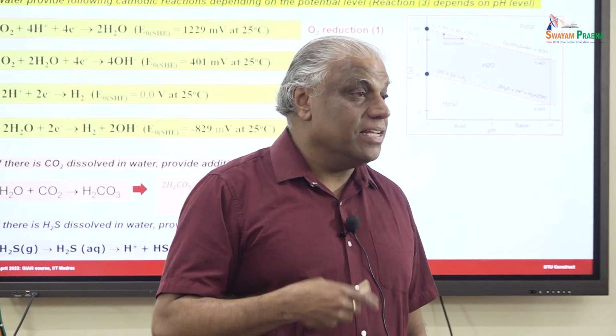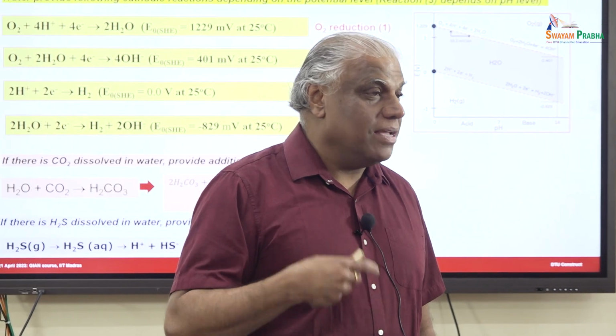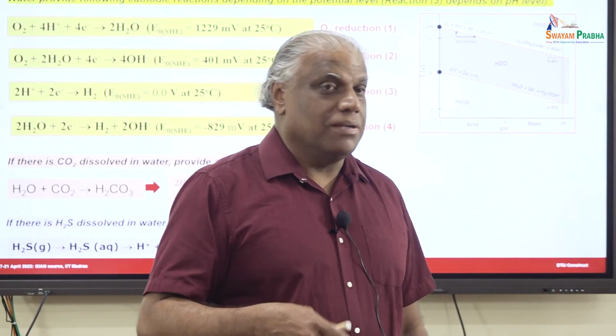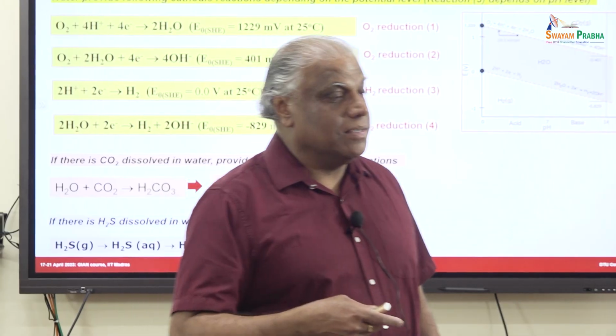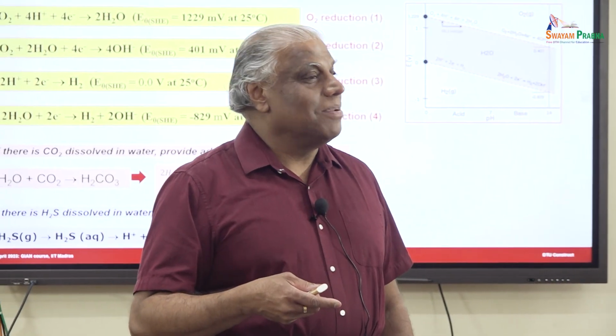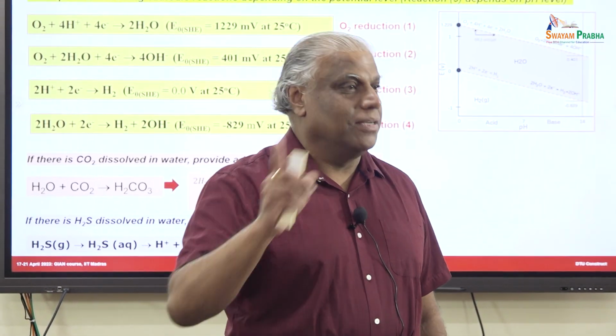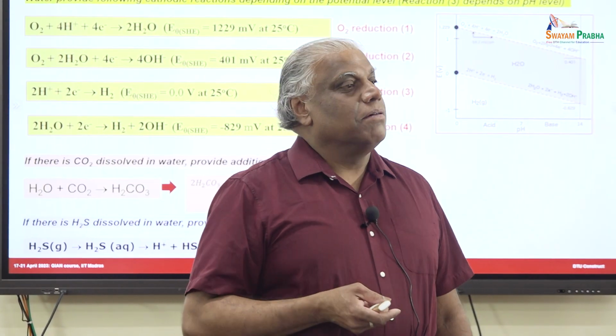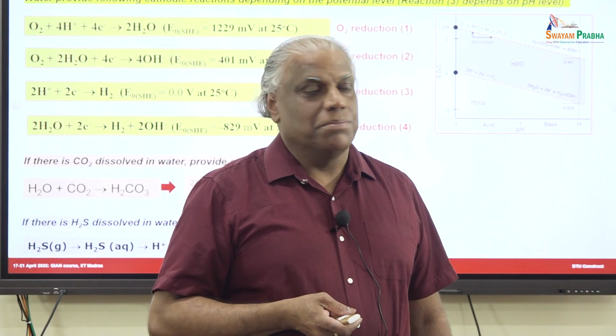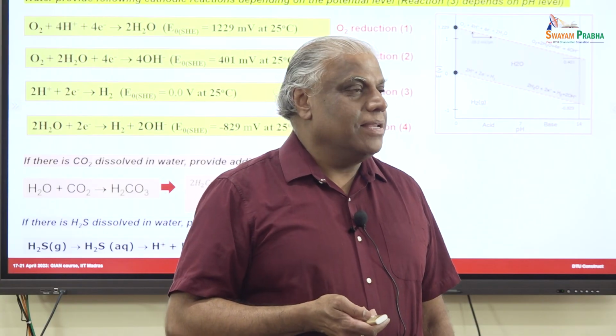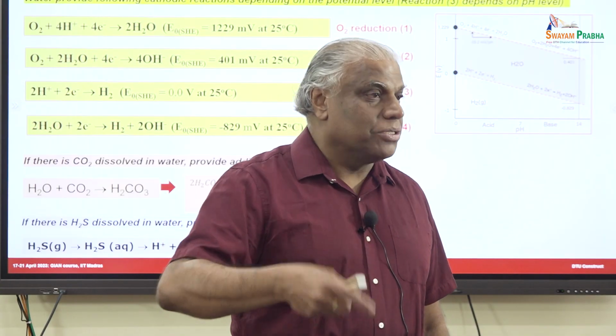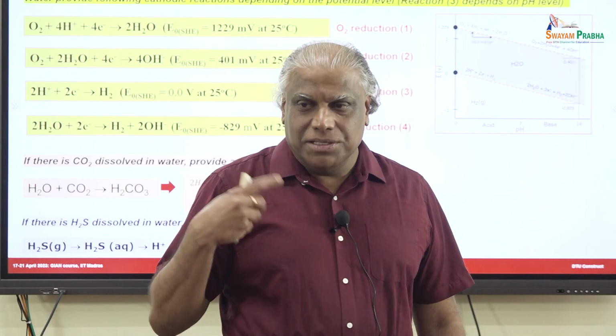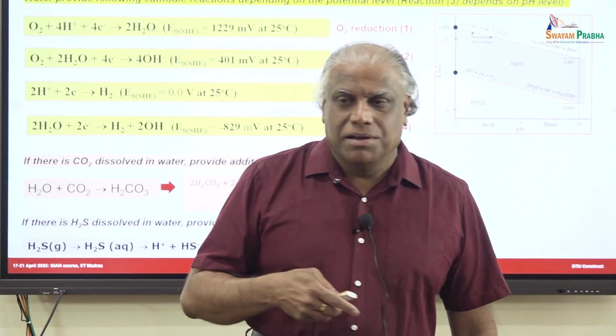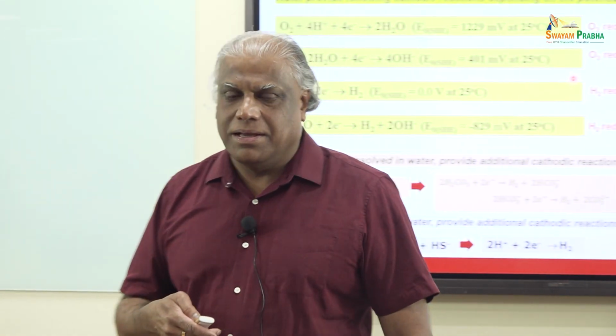That's the reason that in the heat exchangers, in the wind turbine, there is a heat exchanger sitting. They need to use hundreds of liters of solution in that heat exchanger. They remove the oxygen from the system because then they can reduce the internal corrosion of the tubing of the heat exchanger. That can be reduced by removing the oxygen, and in addition to that they add the inhibitor. So that's what I want to bring out, that removing the oxygen, and that way reducing the corrosion problem, is used in many places.